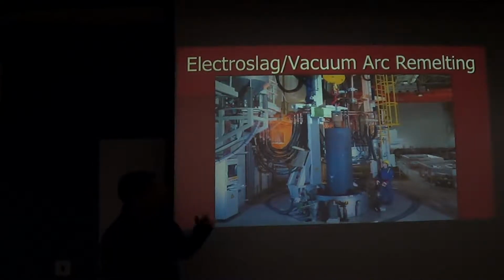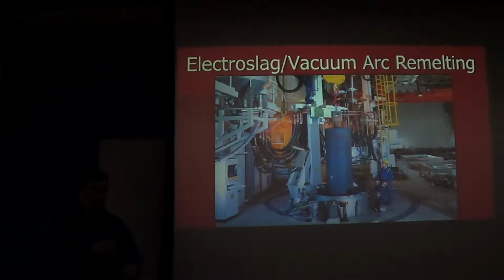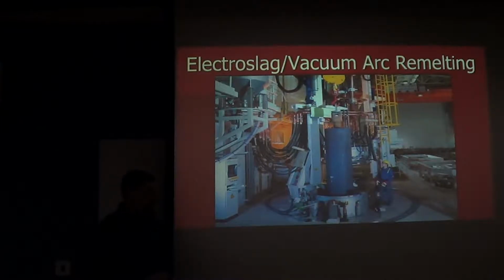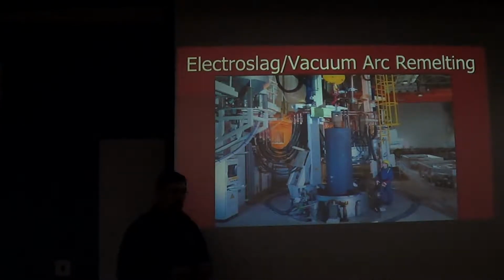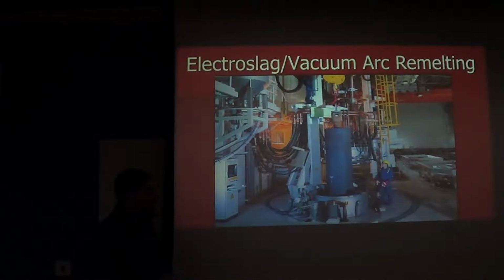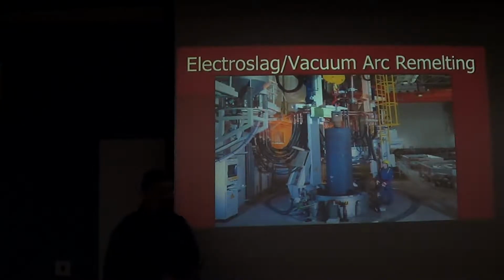And in this particular process, in the electroslag process, there's a slag layer that liquid metal falls through, and that's chemically reactive, much like the slag that's used in the main steelmaking process. That slag is there to help remove any little bits of non-metallic material that may have been entrained during the primary steelmaking method.